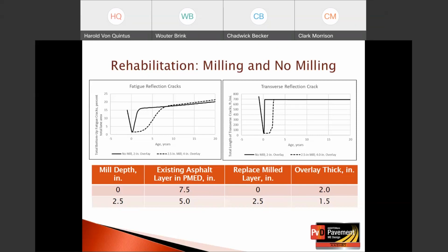So if you're looking at the graph on the left, we have a mill depth of 0 on the black solid line, where those cracks are going to propagate fairly rapidly. And then by milling that, remove and replace, that's the dashed line where we're putting on only 1.5 inches more asphalt, but the total new asphalt is basically 4 inches. That's the replaced mill depth plus the overlay thickness above the mill material that is replaced.